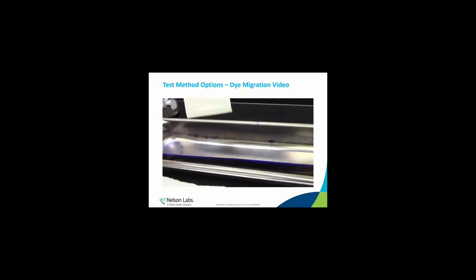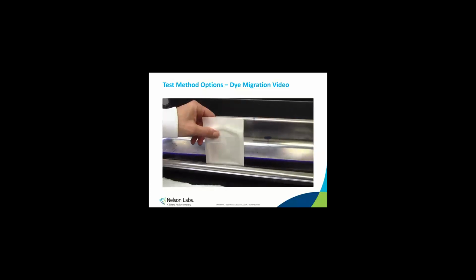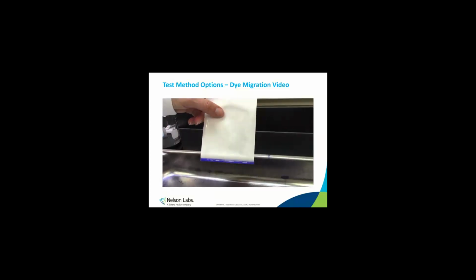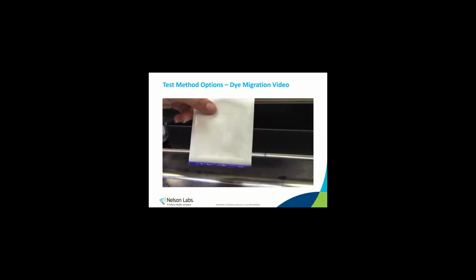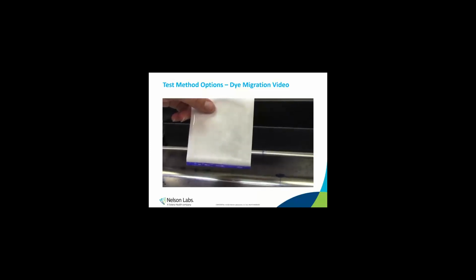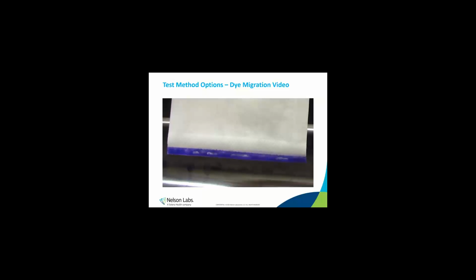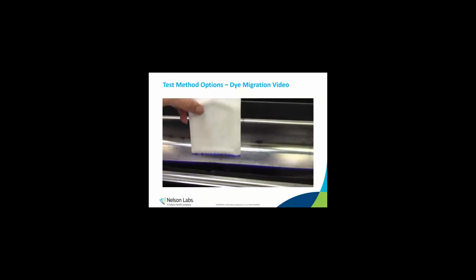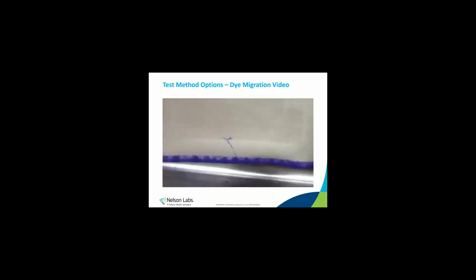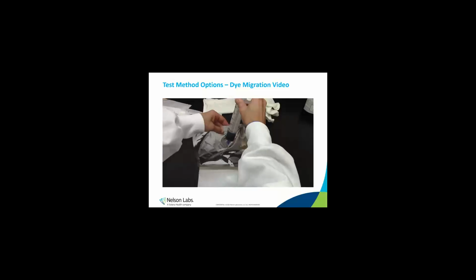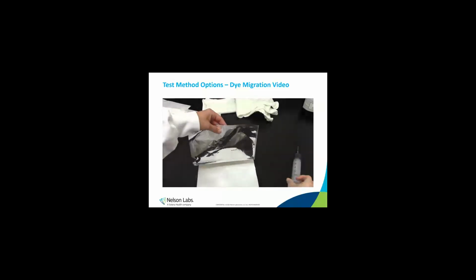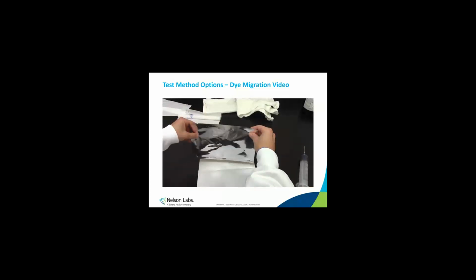That's a 50 micron wire. If we're doing the edge dip, we just dip the edge of the sample into the dye, we pull it out and look at it. This one here is a good seal. And here's, look how fast this channel appears. It's almost instantaneous.